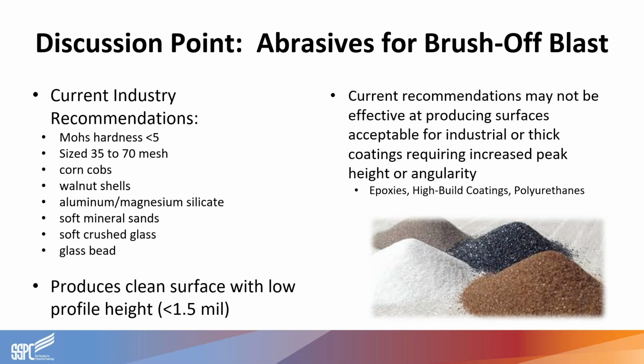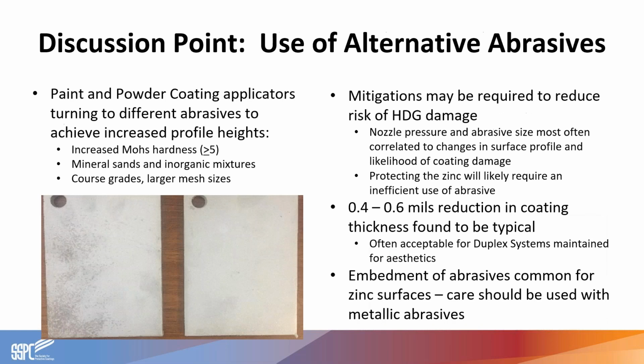But these recommendations may not always fit the bill if you're trying to achieve the type of rough surfaces required for maybe thicker coatings or industrial grade coatings that may require significant profile height or angularity, such as your epoxies, your high build coatings, polyurethanes. So in the marketplace, to get around this type of issue, specifiers and applicators have been looking outside of the typical abrasive recommendations, and instead they've been turning to harder or coarser sizes available from mineral sands or other inorganic products and mixtures.